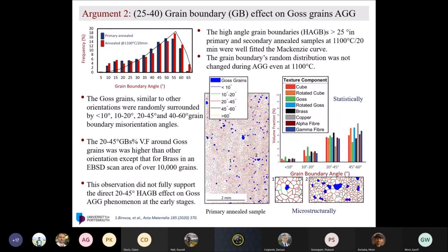So here, first of all, we look at the volume fraction of all the high-angle grain boundary from 15 to 65, and the graph perfectly fitted the McKenzie plot, and that McKenzie plot made it obvious that the grain boundary was randomly distributed, ignoring the fact that the small or low angle grain boundary, even below 20, is different. Let's say this is a different distribution, but for high angle it was rather random. Now we did the same thing. We separated all the grain boundaries. For example, smaller than 10 degrees we highlighted in blue. Between 10 to 20 we highlighted in green. Between 20 and 45, which is the main focal point we want to understand here, highlighted in red.